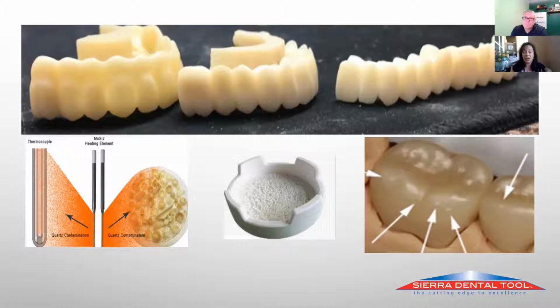Another thing that happens with these heating elements is just the natural lifespan of the elements. It's just what happens as we use them. There is a little bit of iron inside of those elements as well, and when the quartz comes off, it rips off some of the iron. Iron is actually one of the elements, there aren't many, that discolor zirconia. You will see kind of an orangey or very dark yellow hue on your restorations. That's a clue. Geez, I might need to look at my heating elements and check them out, and maybe I need to run a purge cycle. And the purge cycle is real easy.